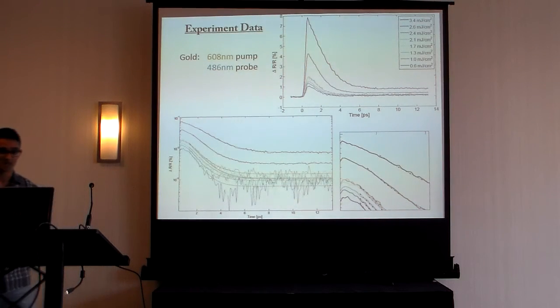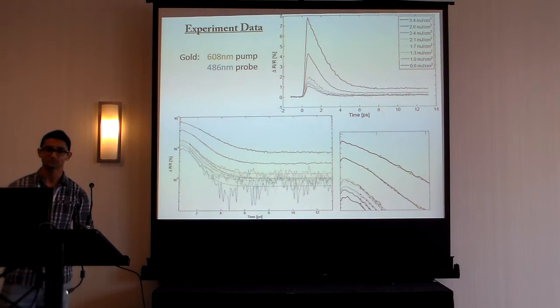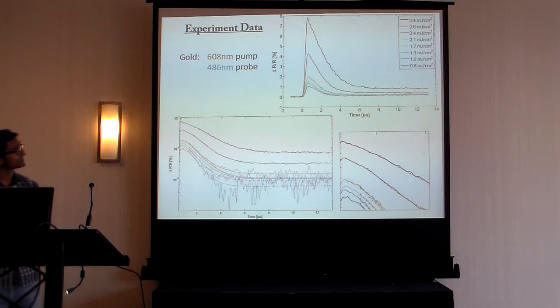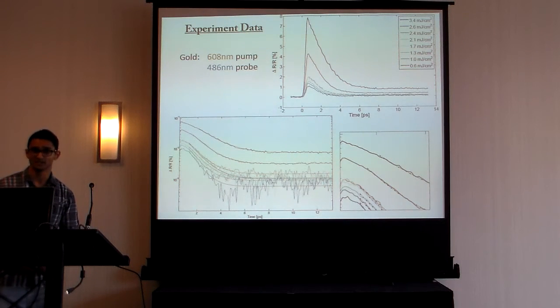So over here we have some sample data for optimal conditions on polycrystalline gold at 608 nanometer pump and a 486 nanometer probe. The differential reflectivity signal is shown on the y-axis as a function of time for a wide range of pump powers. And as you can see, the equilibration process is completed within 4 to 8 picoseconds, depending on the total power of the beam.